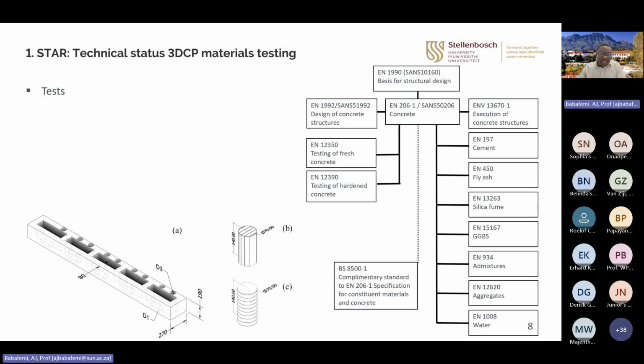Sometimes we can print different sacrificial samples and then take our samples from different directions. As you know, in 3D printing, the material is a layer by layer deposition. So the effect of anisotropy is very, very important. So we take from different directions to look at the influence of the printing direction.